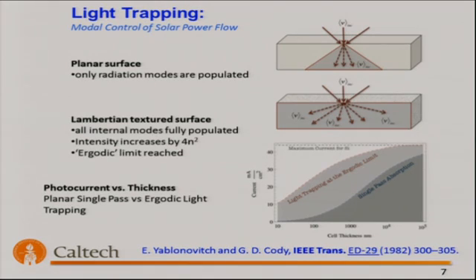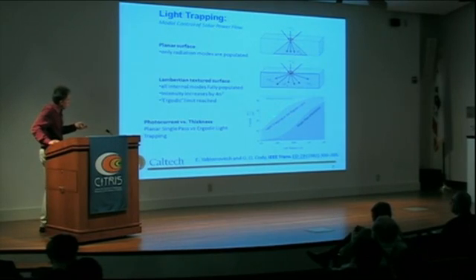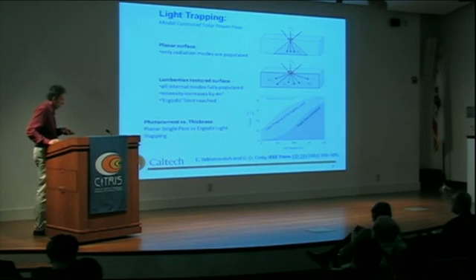I wasn't here this morning, but I feel sure that Shanhui Fan probably shared some thoughts about this with you. But it's an important step forward because it really set the bar for what the absorption in a semiconductor can be, and it represents an opportunity for not only the current, making sure that we absorb light and have enough photocurrent, but we are also able to improve the open circuit voltage. This now represents an opportunity to increase the photocurrent here, as shown prototypically for a silicon solar cell versus cell thickness. You can equivalently think that if you had a target photocurrent in mind, you could make the cell thinner by achieving full light trapping at this so-called ergodic limit, where all of the internal modes are populated.